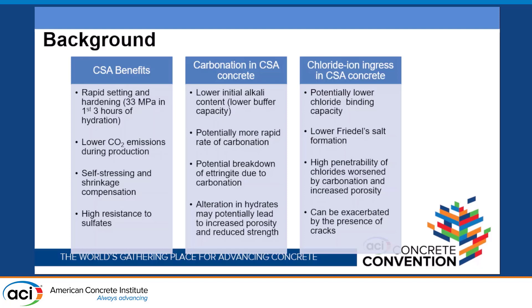With carbonation, most literature has reported low alkaline contents in CSA concrete, and also a potentially more rapid rate of carbonation, which leads to a potential breakdown of ettringite phases due to carbonation. With chloride ion ingress, there is a potential lower chloride binding capacity of this binder, which could lead to lower Friedel's salt formation, and high penetrability of chlorides could be worsened by carbonation and the increase of porosity in this concrete.